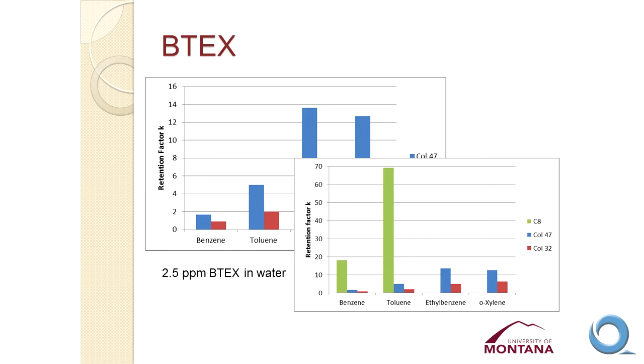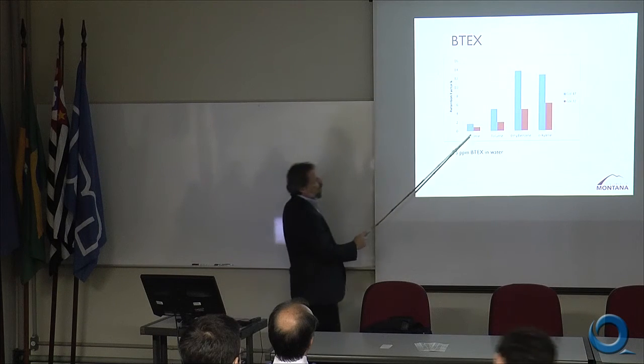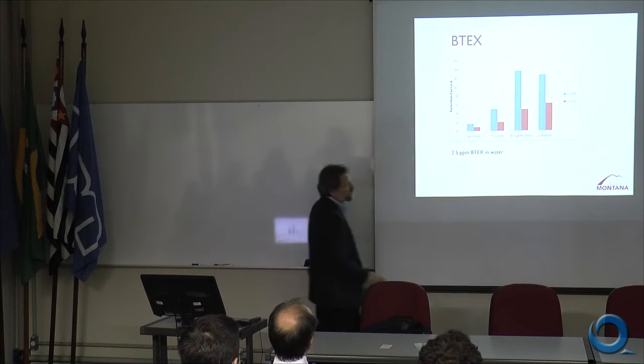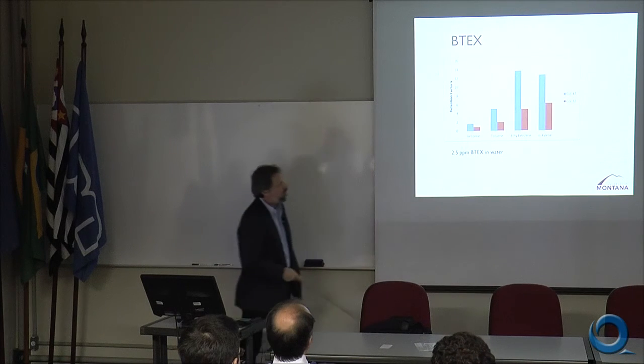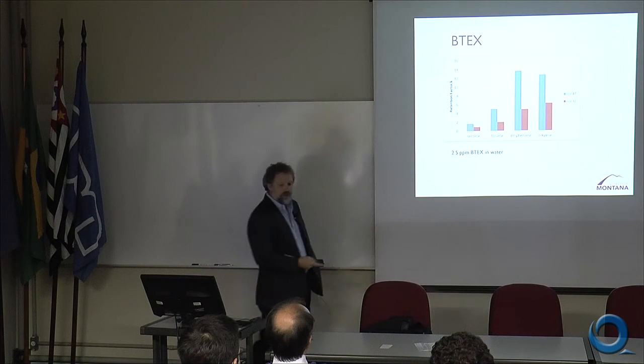Okay. We looked at benzene, toluene, ethylbenzene, xylene. These are obviously components of gasoline, and they are often found in groundwater around gasoline stations and refineries and places like that. So it's an interesting problem. We looked at the retention of benzene from water on a column coated with the nanoparticle 47, and a column coated with the nanoparticle 32. And we do see some significant retention of these compounds, and we also see that